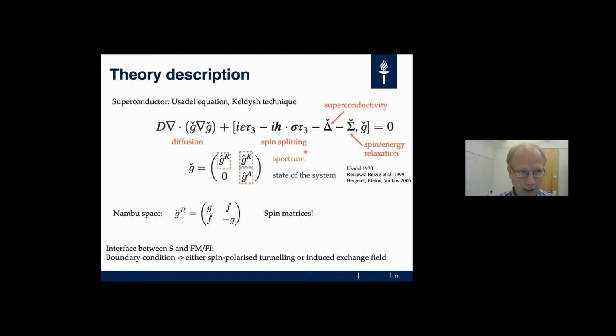This is a diffusion equation for the Green's function of the superconductor, and you can include in the description superconductivity via self-energy, different relaxation terms via their self-energies, and then the spin splitting, which is the exchange field term here. If you describe this Green's function in a Keldysh formalism, you are able to describe both the spectrum, which comes from the retarded and advanced parts of the Green's function, and the state of the system, which comes from the Keldysh part.